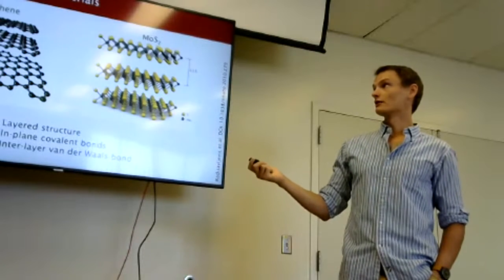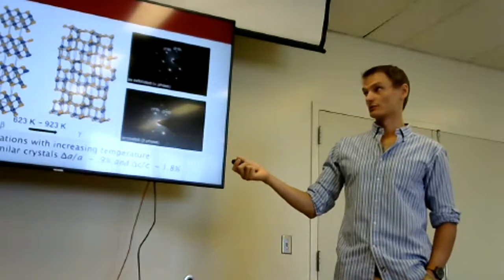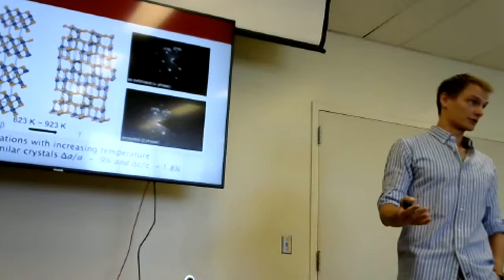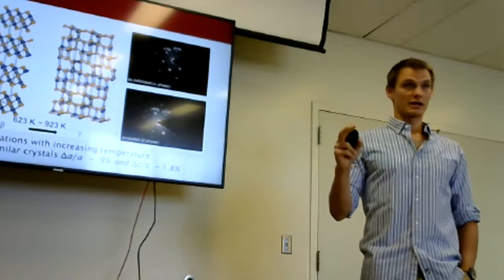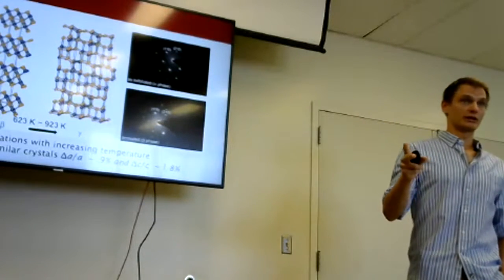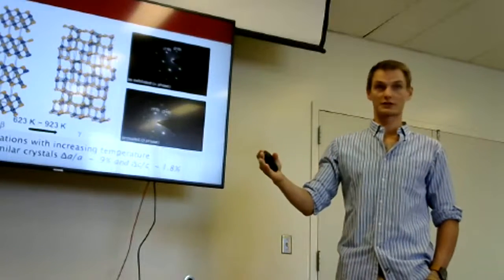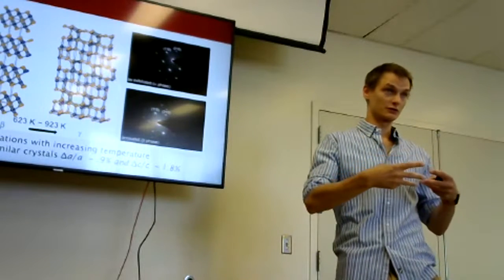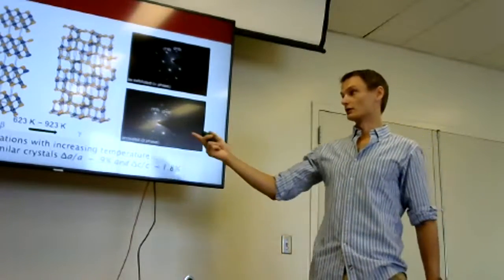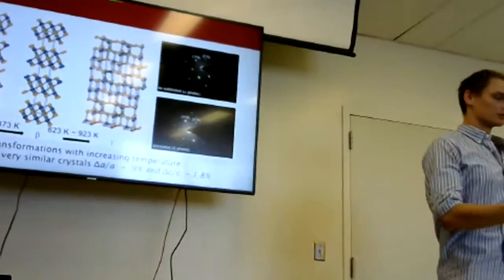But today we're going to talk about indium selenide, which is another van der Waals material that has 5 layers instead of 3. So indium selenide, the thin film, has a lot of crystal phases, but we're only going to talk about alpha and beta here. The reason we talk about alpha and beta will become apparent through the discussion, but alpha and beta have a 5-layer structure with 3 layers of selenide sandwiching 2 layers of indium, and then a repeating crystal. And then they look almost exactly the same for 1 layer, but they repeat differently, as is sketched in this diagram.